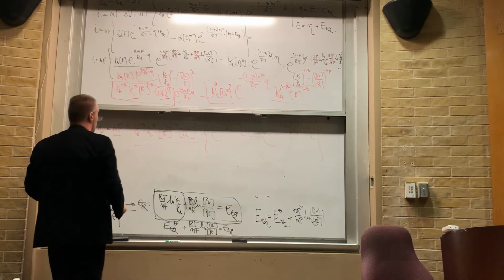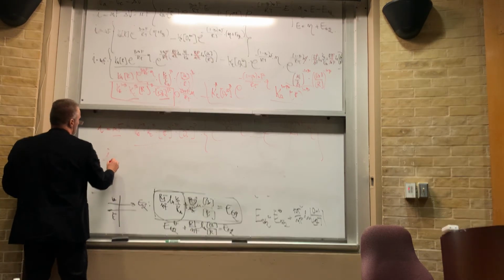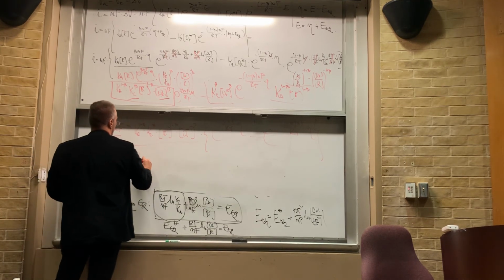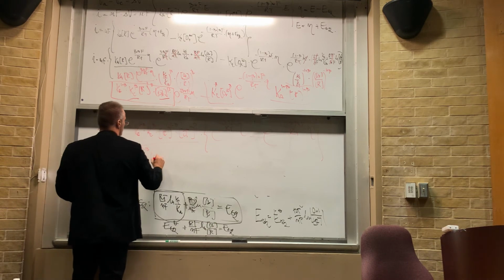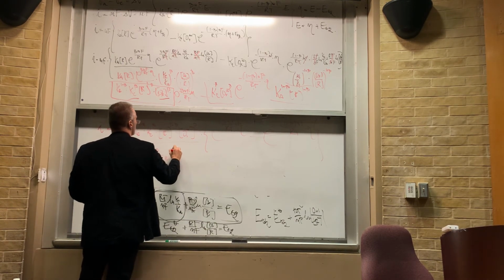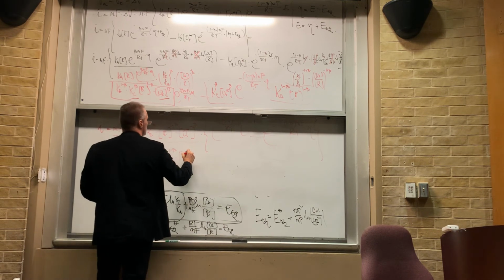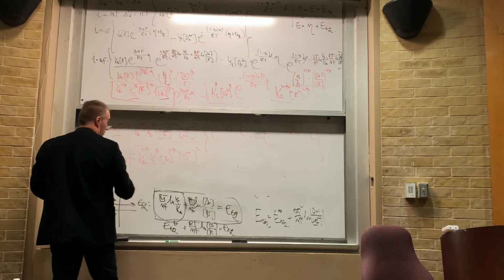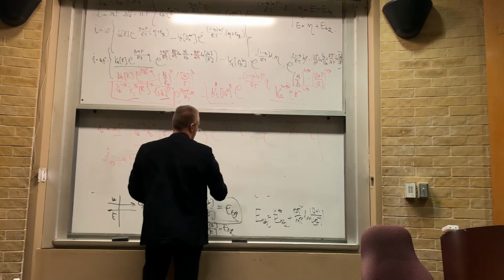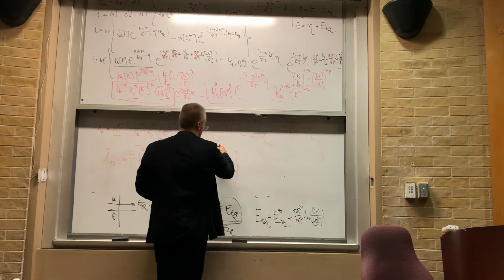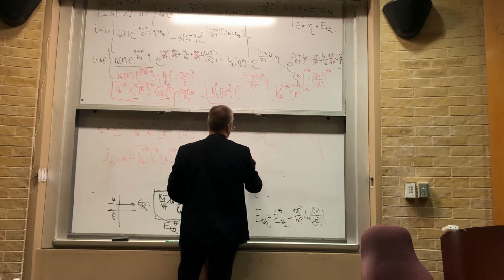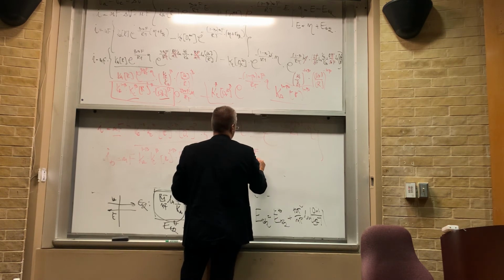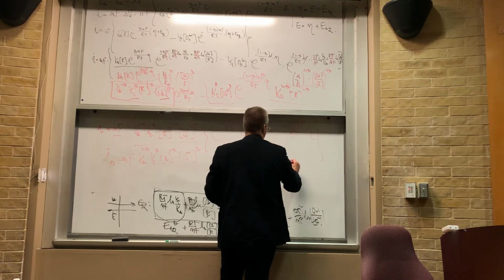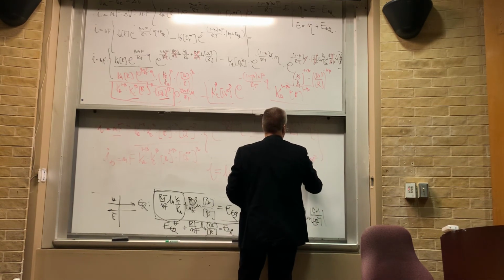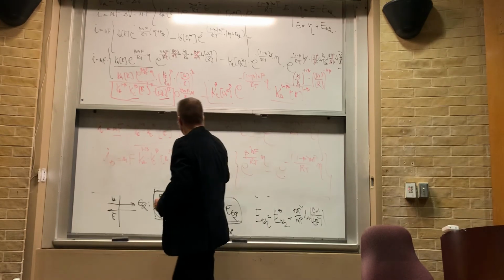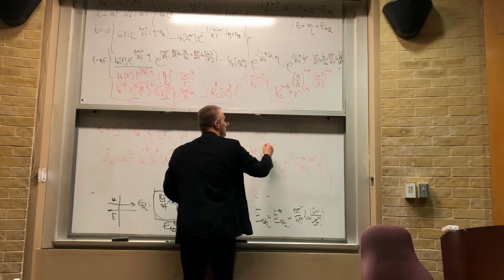This thing can come here together with this one, and basically we're going to define a new term called the exchange current, which is equal to nF Ka to the 1 minus beta, Kc to the beta, R to the power 1 minus beta, oxidized species to the power beta. And so the whole new Butler-Volmer expression is now given as: the current is equal to I naught, which is the exchange current, multiplying the difference in these two exponentials, which is e to the beta nF over RT times eta, which is our potential, minus e to the minus 1 minus beta nF over RT times eta, right? This is the Butler-Volmer equation that describes electrochemical kinetics.